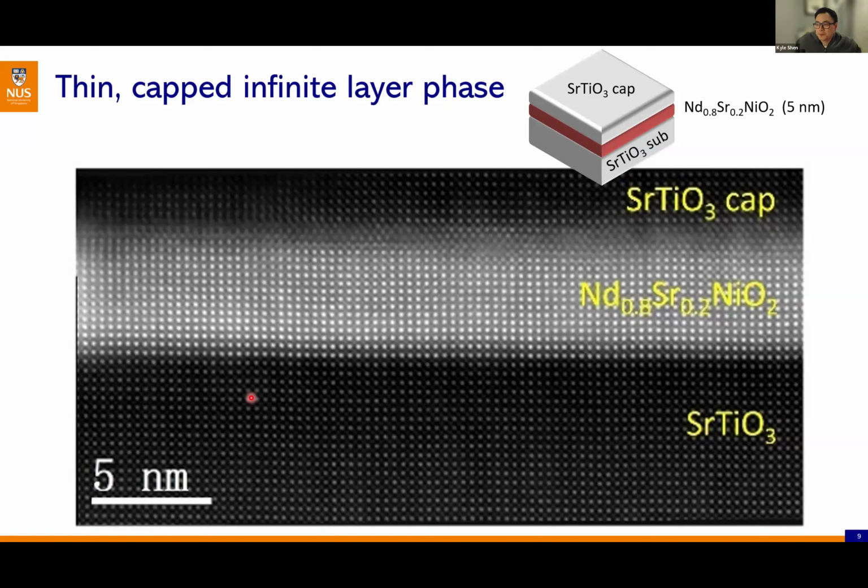Yeah, so I'll just very quickly summarize what we found. I should say that it's restricted just to the neodymium nickelate. As Harold alluded to, we haven't looked at the lanthanum nickelate, but in the neodymium nickelate, what we found is that when you reduce the perovskite from neodymium nickel 3 to neodymium nickel 2, it doesn't progress directly, but through the formation of a brownmillerite-like phase, which has 1/3 of the apical oxygens filled.